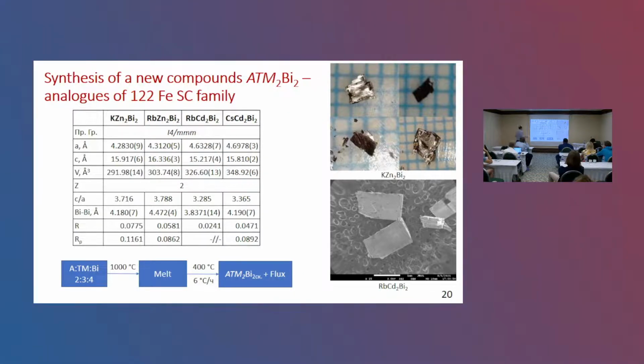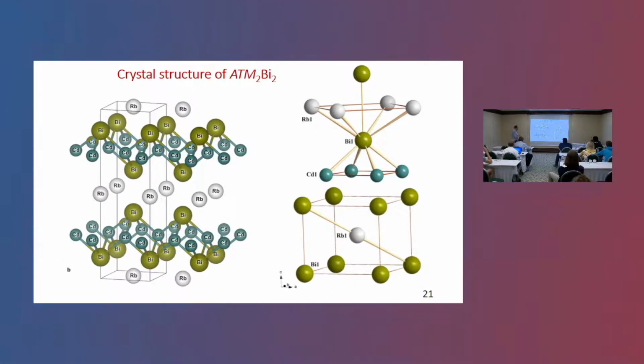But in the case of rubidium cadmium 2 bismuth 2, after a very large number of experiments, one crystal was okay, and then we could use these results as a model, and the structure was determined from X-ray powder diffraction data. In this picture we can see the structure of this compound. We can see antifluorite-like layers, like in 111 and 122, and in all iron-based superconductors.